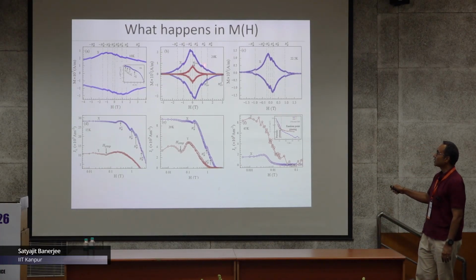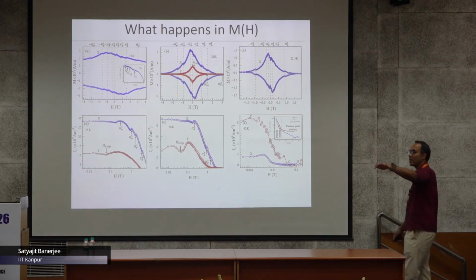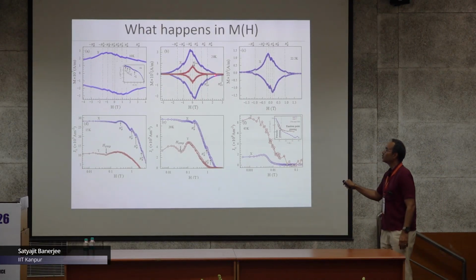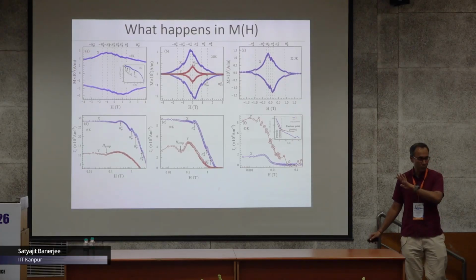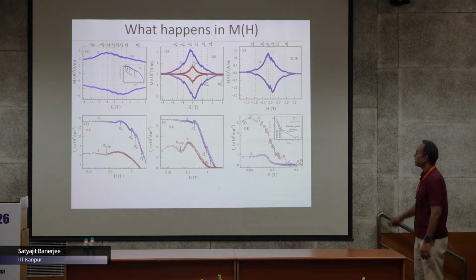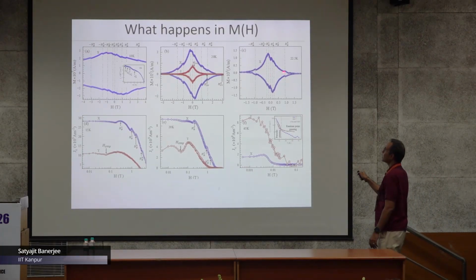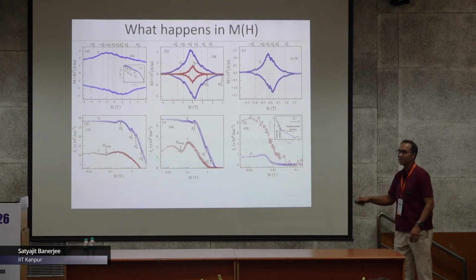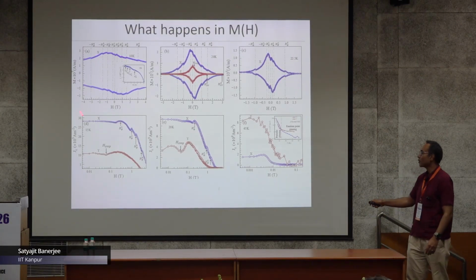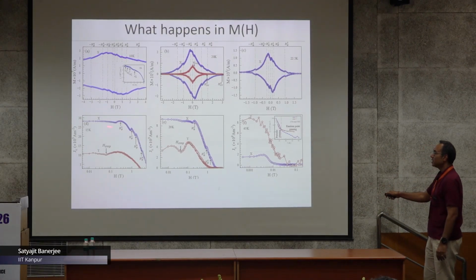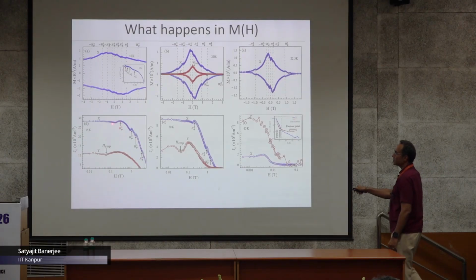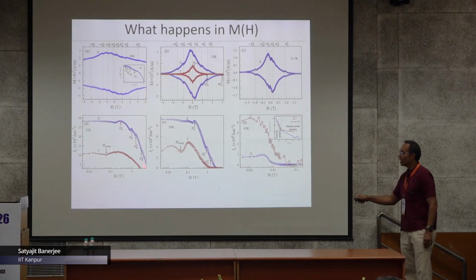If you go from sample X to sample Y, which doesn't have these periodic modulations, you see that it is almost smooth - you don't get these periodic steps. As you increase the temperature, these steps slowly disappear. If you measure the critical current of the superconductor, you can see these modulations very clearly.